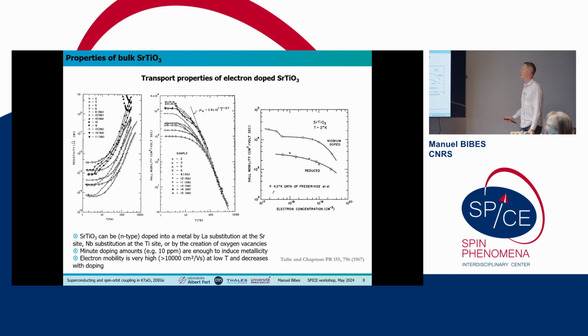I just want to go back to the properties of strontium titanate because I cheated a little bit when I was saying that you take two insulators and you have a metal at the interface. This is true, but in fact, if you go back to the properties of strontium titanate, yes, it is an insulator, but it's quite easy to make it metallic. If you dope it with just 1 part per million electrons, it already becomes metallic.